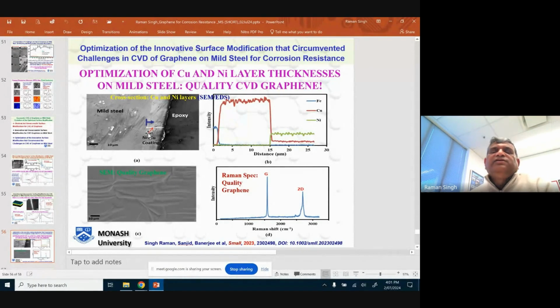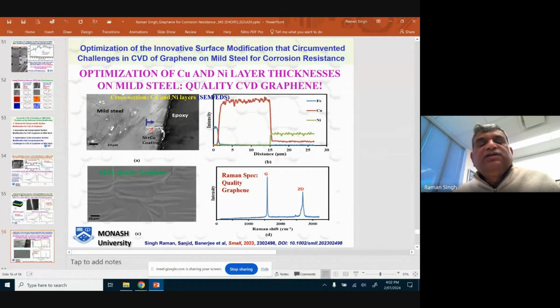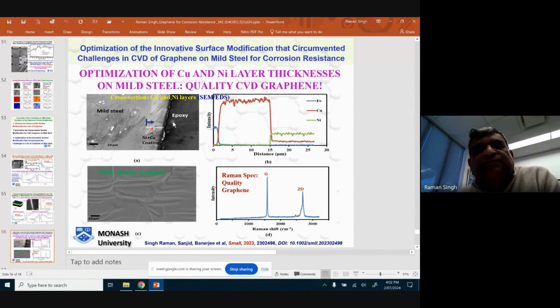So what we did, we undertook very good diffusion calculations of what is the length to which iron, carbon and copper can diffuse during the time and temperature window of CVD. We don't want iron from the matrix to diffuse to the surface and jeopardize graphene development. We don't want even copper to come to the surface because copper will also not allow multi-layer graphene development. So we optimized the thickness of the layer, taking into account the CVD time and temperature, and we came up with about 10 to 12 micron to be safe.